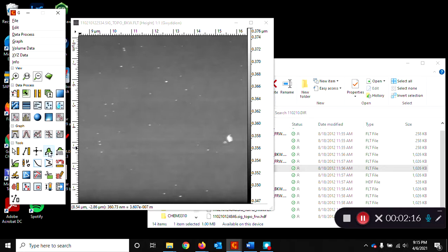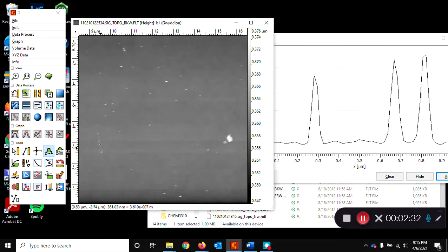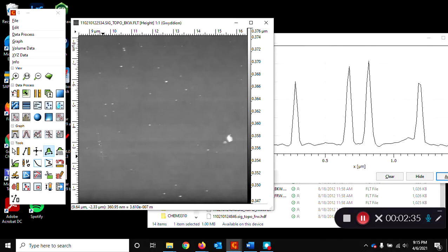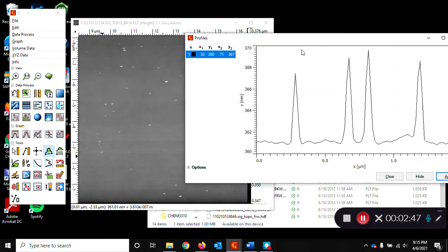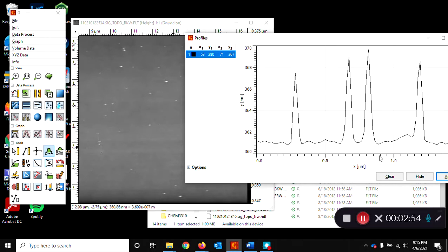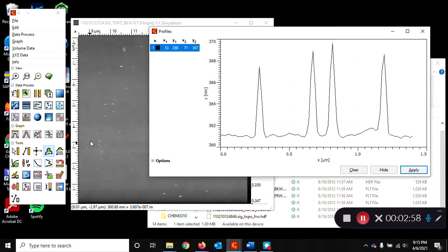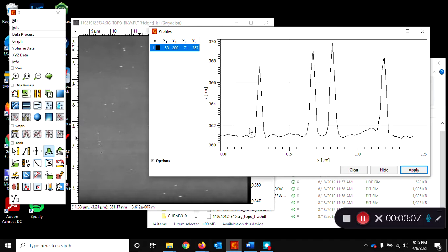To do that we're going to extract a profile of this topographical data. So this is the window to show us the profile line as we draw it and what I usually do is I try to draw a line that's going to go through multiple points. And you want to make sure the line's going through the center of each point so that you're getting the maximum height of that point. So here you can see this is zero microns starting at the start of the line here to about 1.5 microns. That's the full length of this line here. So this bright spot right here is actually this peak which is a cross section of that particle that's there.